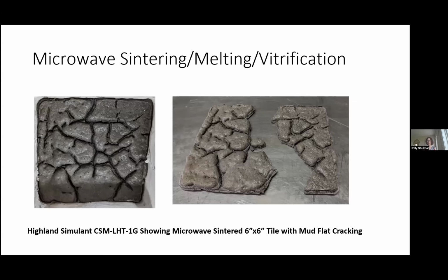Okay, so again, starting out, I'm not sure what's going to happen. Top down heating. This was actually in my lab, in a cover gas of argon. This was my major concern, that we would have something called mud flat cracking. If you've ever seen mud that has dried out, it's got this pattern, these cracks. What that is, is the drying of that mud. It's coming out from the surface and it can't shrink laterally. So you have a condition where it just sets up cracks. And this is what I was really worried about. And there it is, of course.